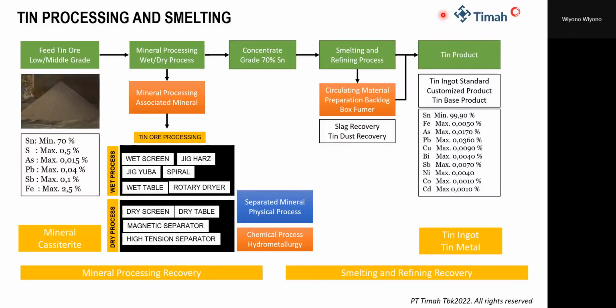And then in smelting, we also smelt the circulating material. We call it backlog. There are several types of circulating materials: dross, tin dust, and hard head. We recover the circulating materials to get a higher recovery in our smelting. And then we also recover slag in the second stage of smelting. It's also to increase the recovery of the tin smelting.